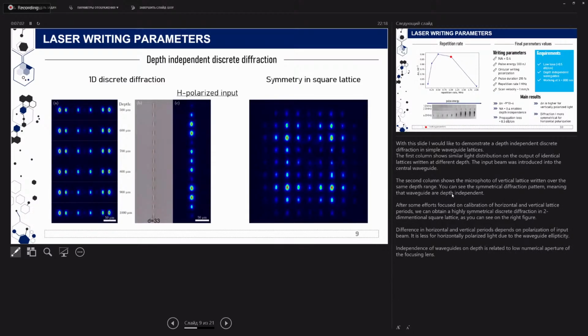With this slide, I would like to demonstrate depth-independent discrete diffraction in simple waveguide lattices. The first column shows similar light distribution as the output of identical lattices written at different depths. The input beam was introduced into the central waveguide. The second column shows the microphoto of vertical lattices written over the same depth range. You can see the symmetrical diffraction pattern, meaning that the waveguides are depth independent.